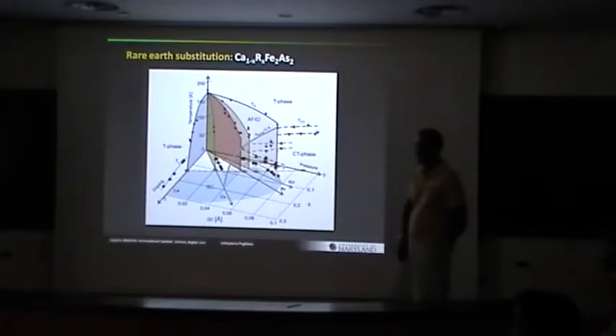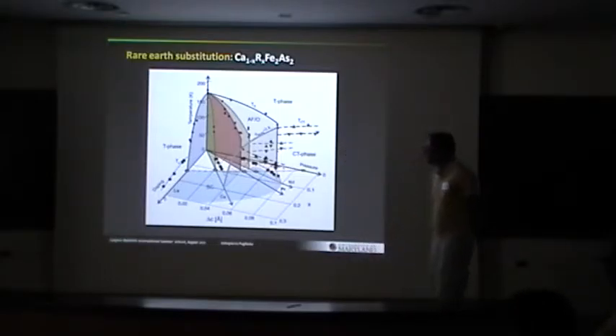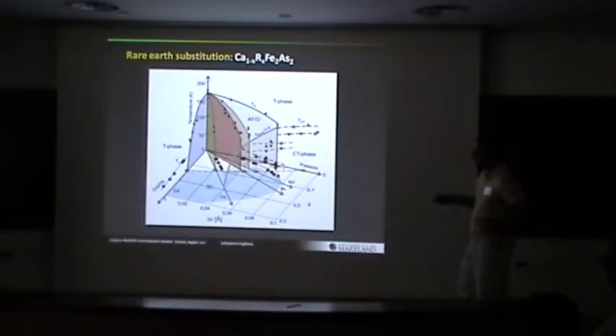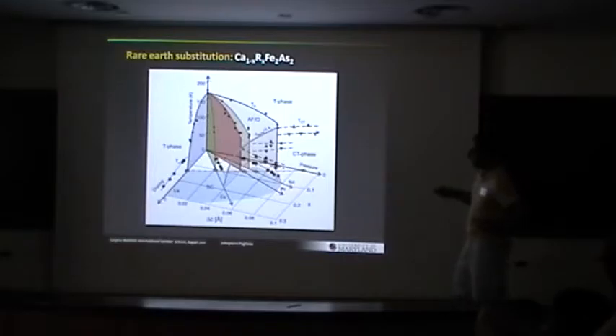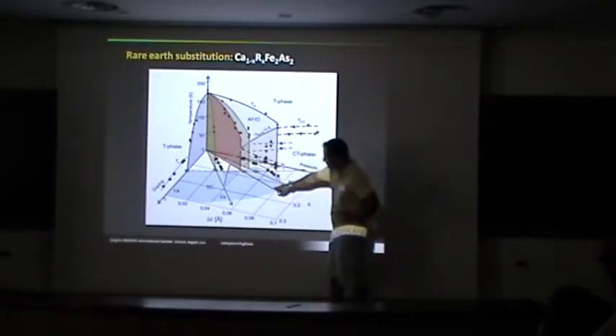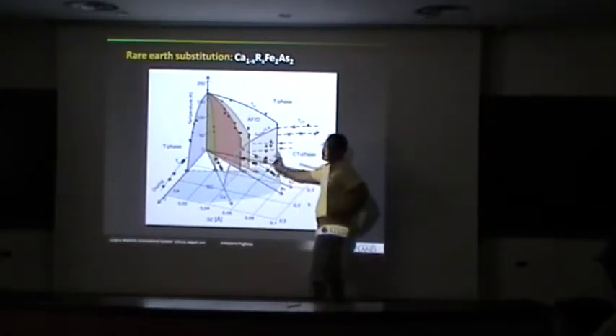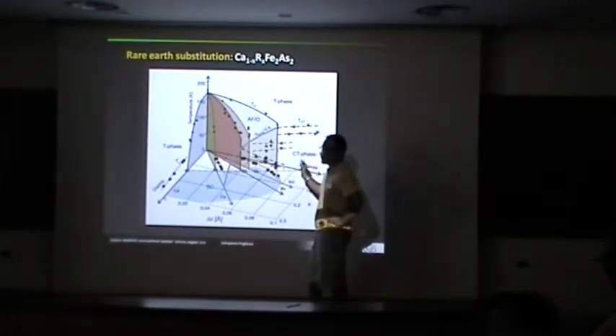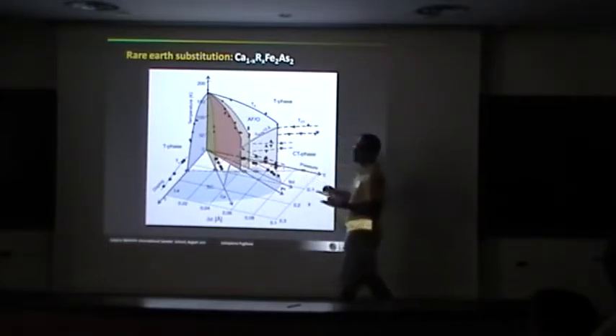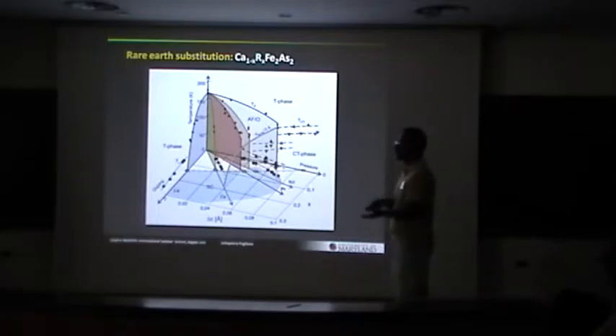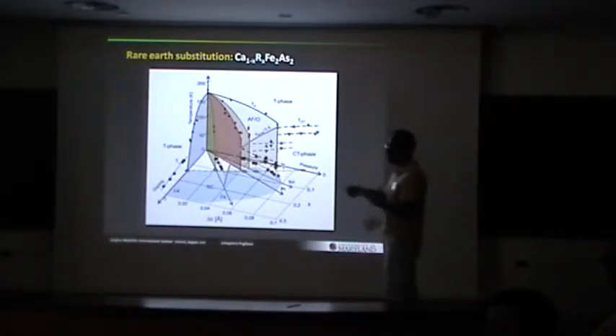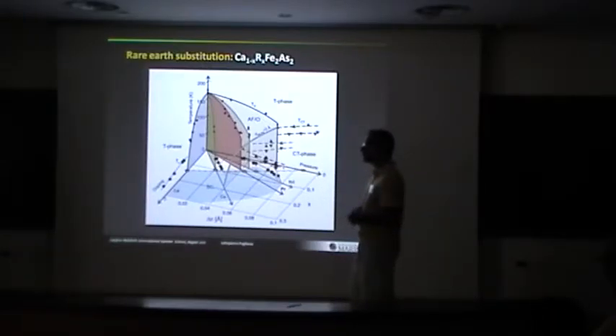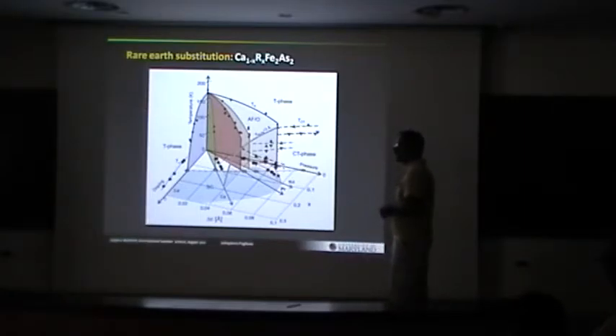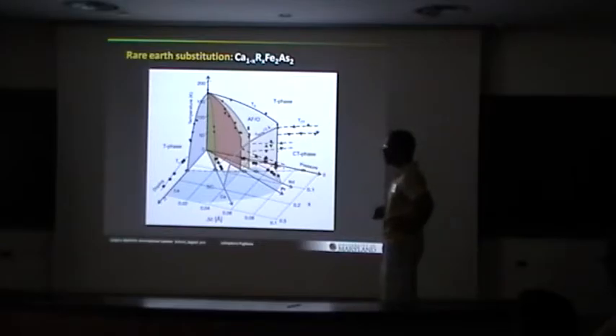So what's the statement now regarding superconductivity? Only occurs in the collapsed phase, of praseodymium, let's say? From what we observe, it occurs in the rare earth doped samples that show the collapse, praseodymium, neodymium, and also the ones that don't. But the caveat is that maybe it's some foreign phase. To me it's very hard to believe that you have a crystal that undergoes such a dramatic change in structure, and you have enough left over of some non-collapsed phase to have this superconductivity. But it's possible, yes. The collapse transition is always above the superconducting transition. Is that what you mean?